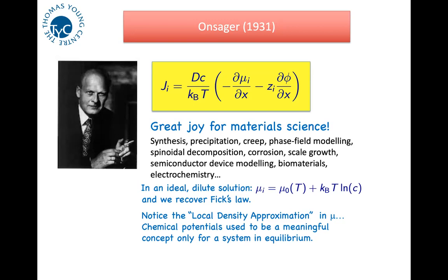this is disturbing, but it's based, of course, on the local density approximation for chemical potential. Not quite the same as the LDA in the electronic theory that we know and love in DFT, but nevertheless, it's a local density approximation because you assume the chemical potential at any place in a material is what it would be if that place was extended infinitely in all directions with the same composition, temperature, and pressure. But then from place to place, it's allowed to vary and material diffuses as a result. Now, so this is a great thing.